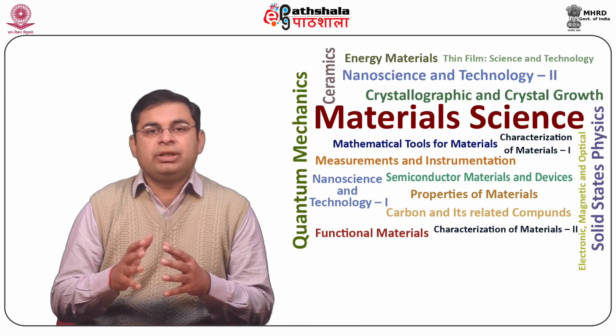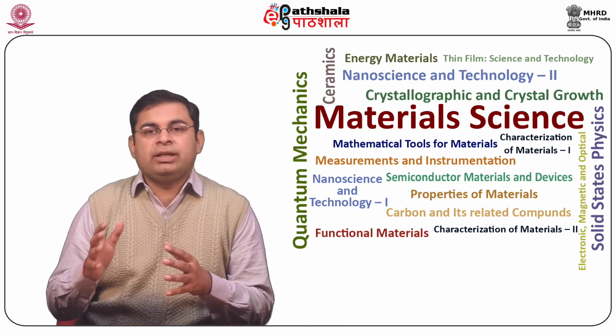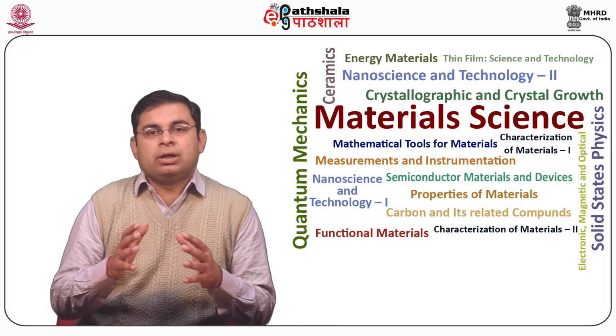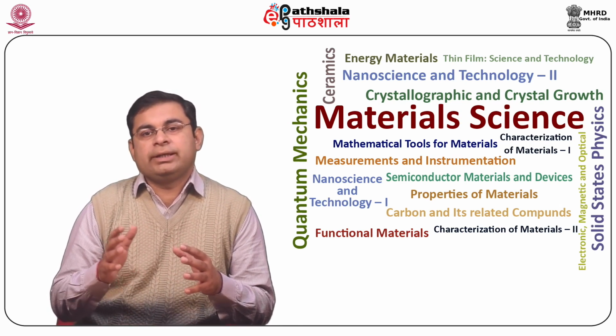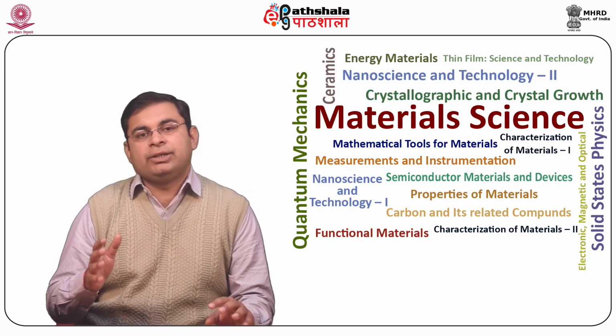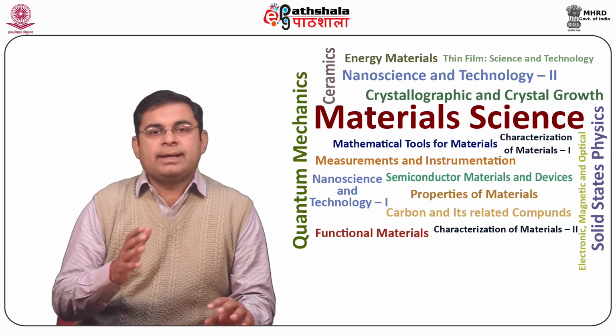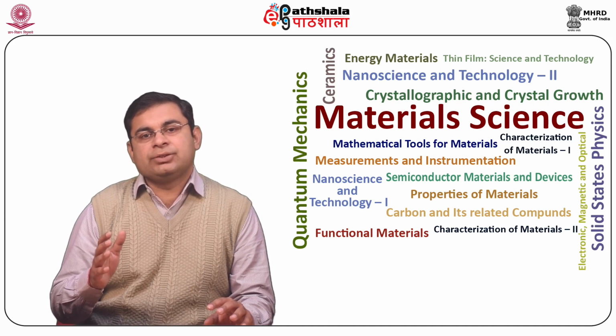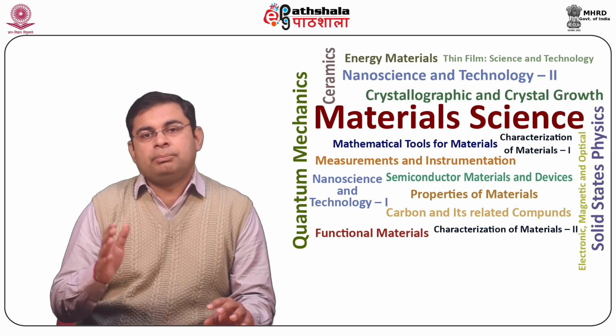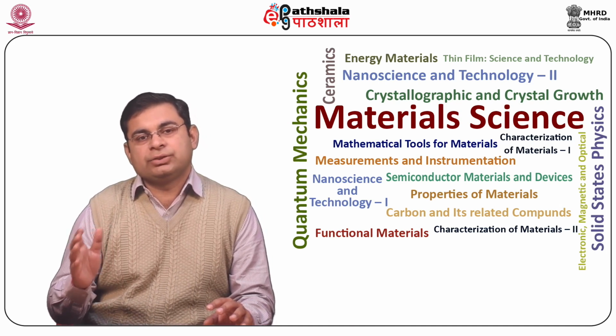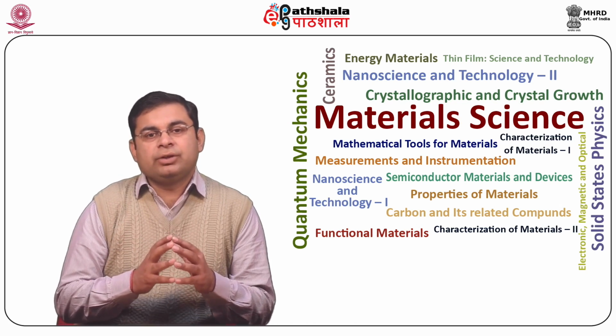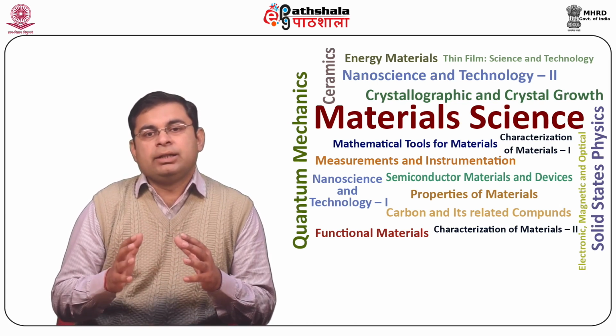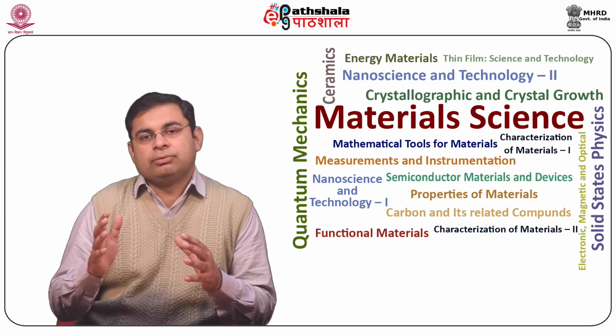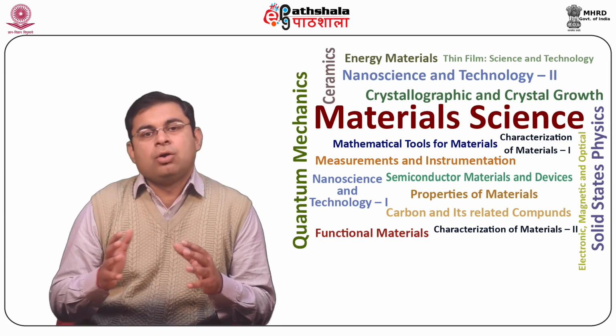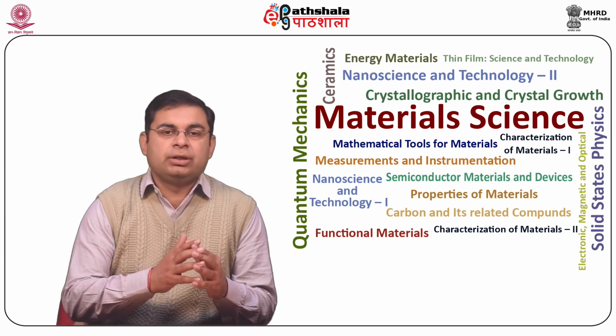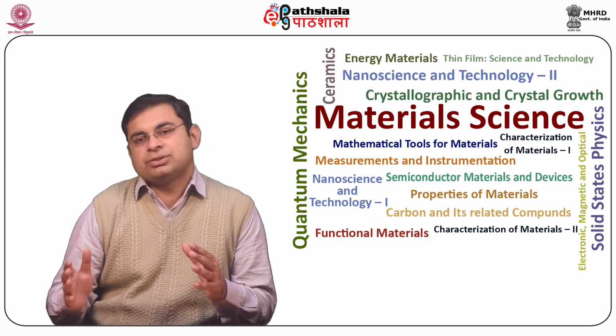While considering a free electron quantum gas, the obtained Hall coefficient is 1 by nq, same as the classical case, along with nil magnetoresistance. The difference in results is more evident when a more realistic model for solid material is considered, for example, crystals.